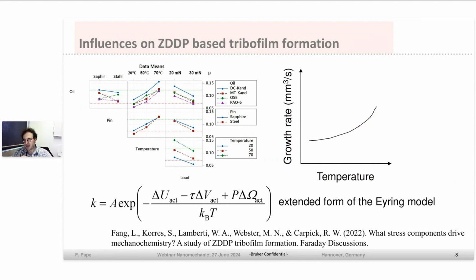That means by increased shear stresses on the surface, it's like a catalytic reaction, we enable the film formation, and by the kinetics, it forms the tribofilm according to the temperature increase, as shown in the diagram on the right. And the third term, the P delta omega activation, this shows us the compressive stress, which also influences the activation energy, but this term is still under discussion by groups like Carpick and Spikes.